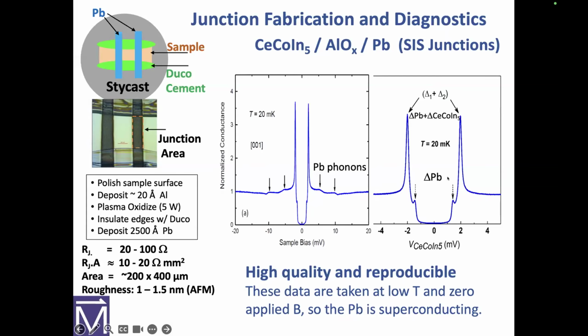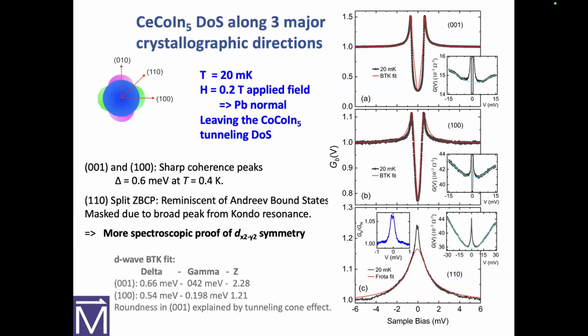CeCoIn5 has a very high Hc2, so you put a little field on it and you drive the lead normal, which gives you a CeCoIn5 insulating normal junction with very little perturbation to get there. So from now on, I'm going to show you all the junctions will be with only about 2 kilogauss, just a little over enough to drive the lead normal.